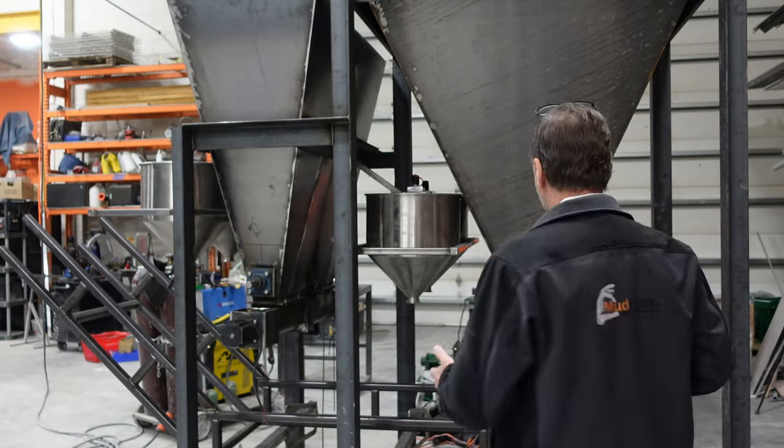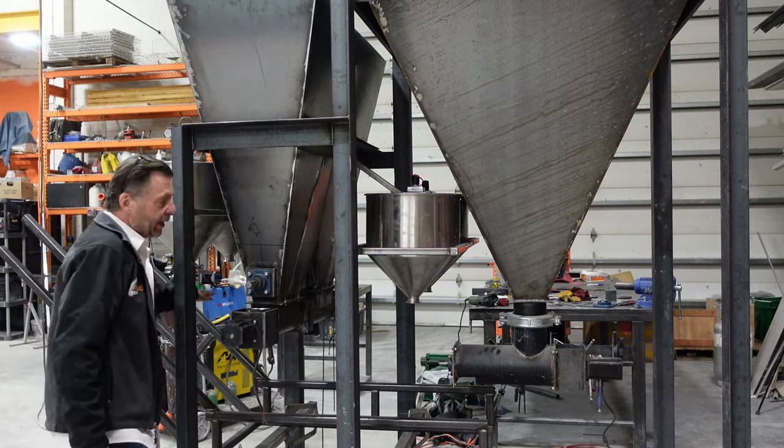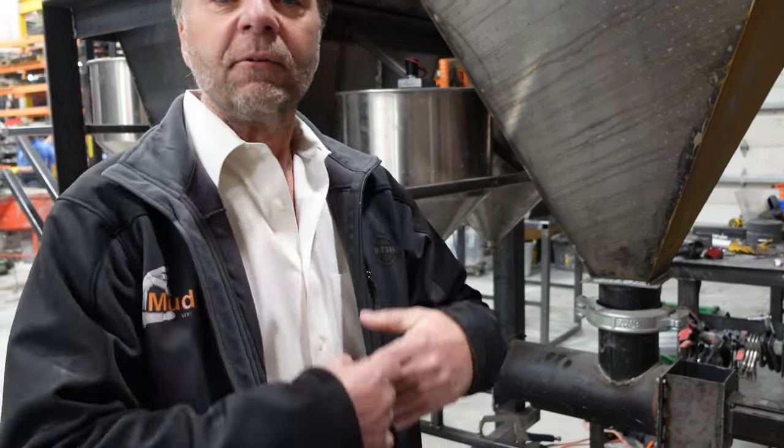The batch plant is automatically metering every one of these — every one has a meter valve. They're motor driven, with quick disconnects on every one of these, whether it's a tri-clamp or larger ones for clearing out material. One of the challenges is getting material to flow, and the higher the humidity or moisture level of your ingredients, it just likes to brick. We've had to put oscillators in all of these, and as with any batching, you've got to try and run with the driest materials possible. The more humidity or liquid you have in your mixes, the more problematic it becomes.